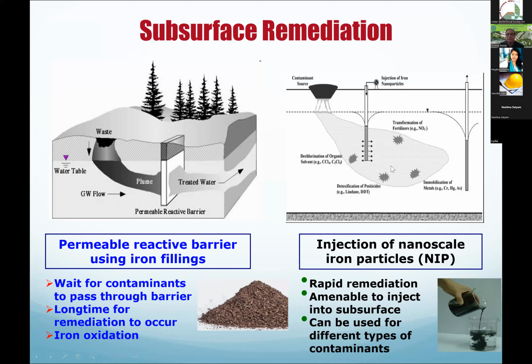The reactivity between the contamination and the nanoiron particles is very, very quick. It's just a matter of introducing the nanoiron particles to the contamination zone, and the reactions will happen really fast. So very rapid remediation happens, and nanoiron particles can be injectable, right? And you can treat different types of contaminants using this. So it's an enormous advantage. You don't have a risk of contamination bypassing your remediation, and remediation taking a long time. Whereas with this one, you are attacking the source. So put the wells where contamination is found, inject it, and be done with it in a very short period of time. So this is the main advantage of using nanoiron particles, very rapid cleanup, not waiting a long time.